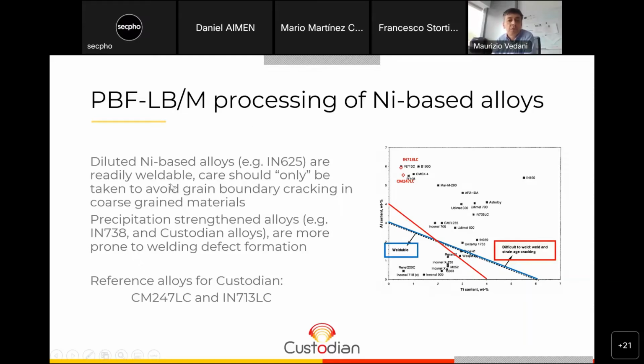So we can draw some information from the weldability of this material, and this has actually been done by considering the plot you can see on the right-hand side of this slide, a sort of map made considering the amount of titanium on the horizontal axis and the amount of aluminum in the material on the vertical axis. The domain is split into 2 fields. On the bottom left corner, we have the weldable materials, more weldable and more processable by PBF. And on the top right corner, you can read some materials that are more difficult to process by PBF and also to weld.